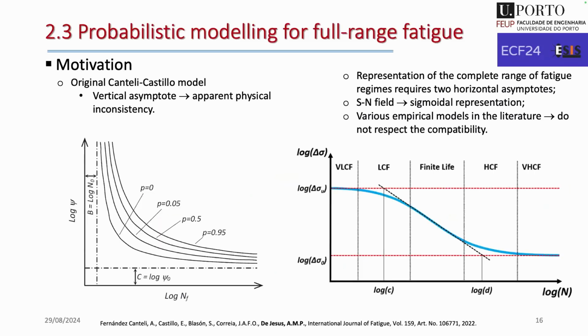One of the shortcomings of the original model proposed by Castillo and Canteli, well, actually, it was understood in the original version as a shortcoming. Later, we realized that it might not be so. We can see here the hyperbolic S-N field, and this vertical asymptote seems to be physically inconsistent, okay? The other one, the horizontal one, is okay because it resembles the fatigue limit of the material. And we should expect, when we are talking of the full SEN field, a sigmoidal representation for the material fatigue behavior when you are using a stress fatigue parameter.